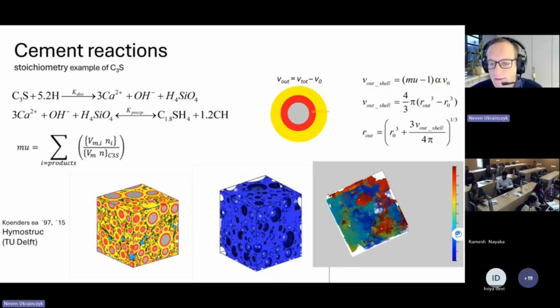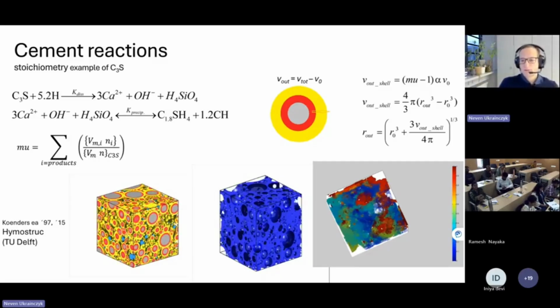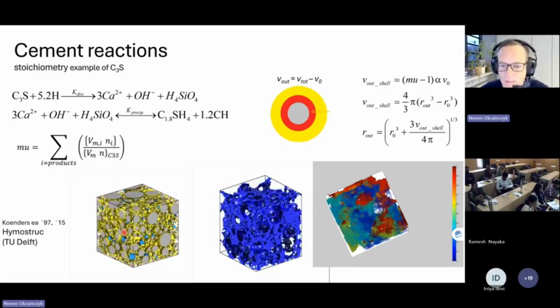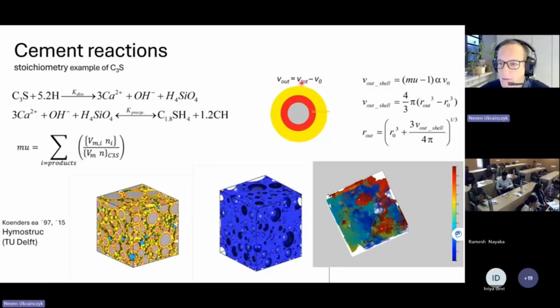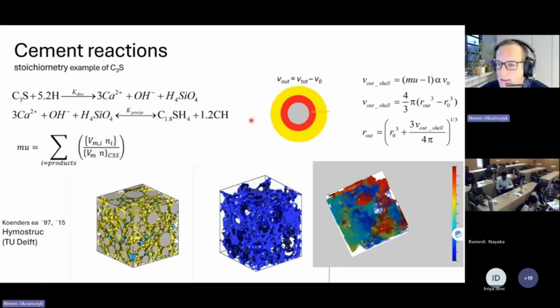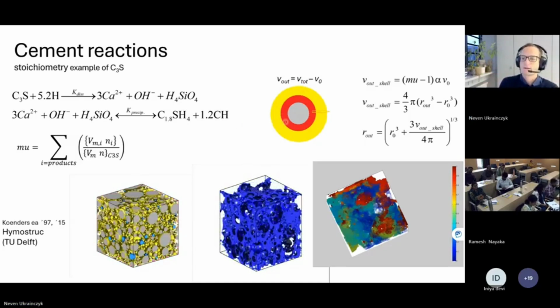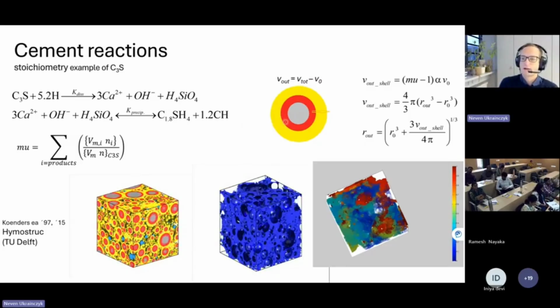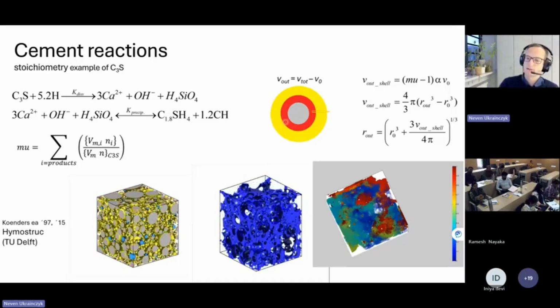The only complicated part is to do it for all the particles, which is also very easy nowadays with computers. But you just need to take care of the volume balance. So you need to take care of the overlaps of each particle. If you have another particle here, they are overlapping. Each time they overlap, by the amount of overlap, you should increase both particles which are overlapping.